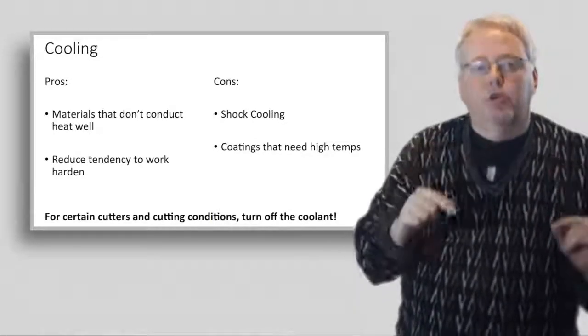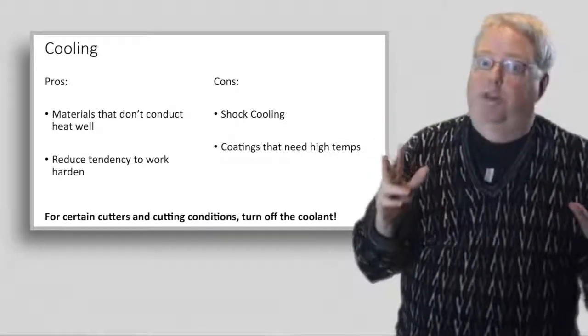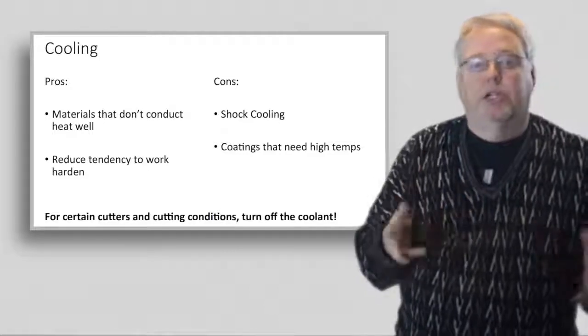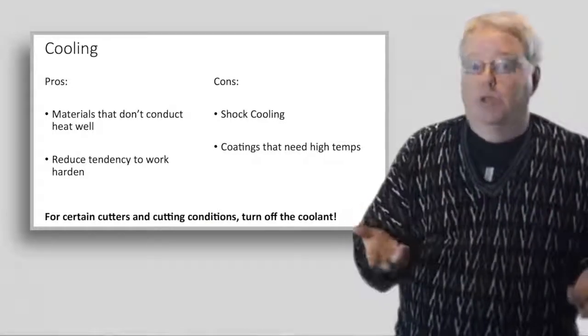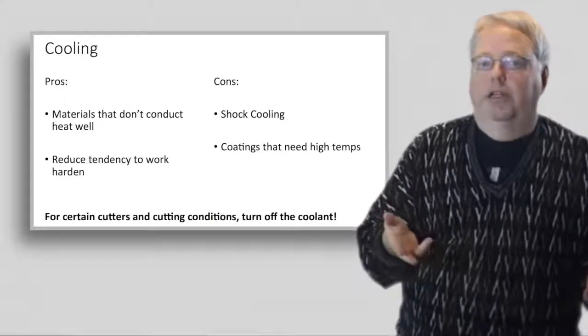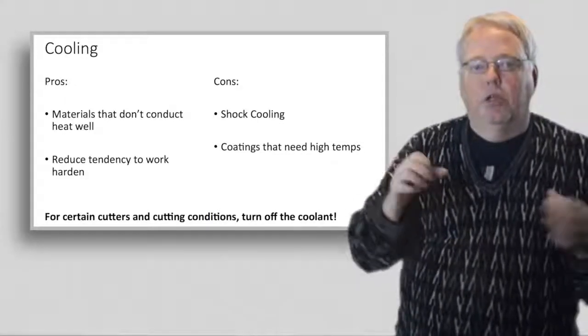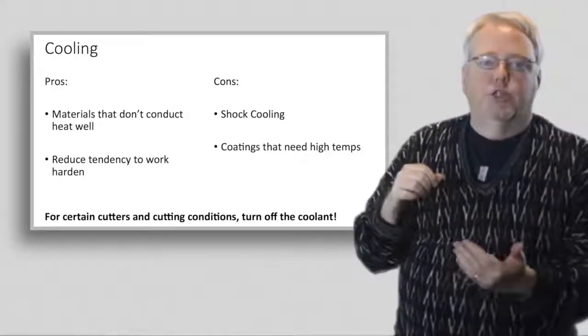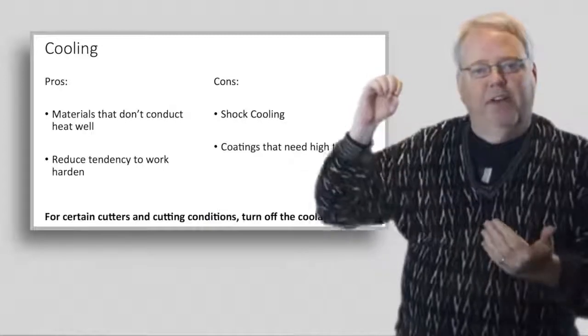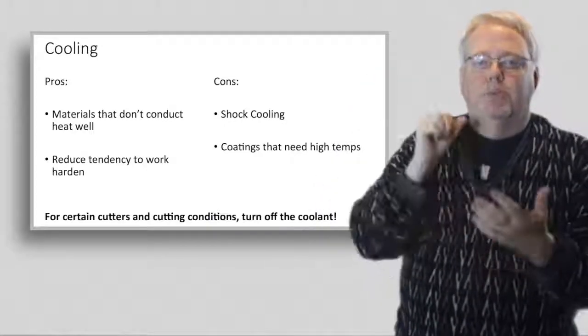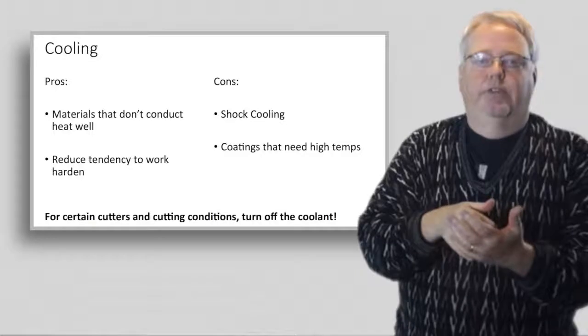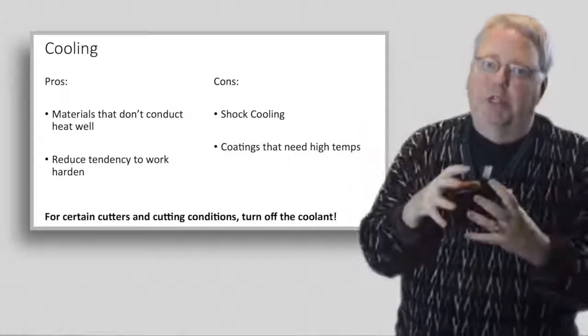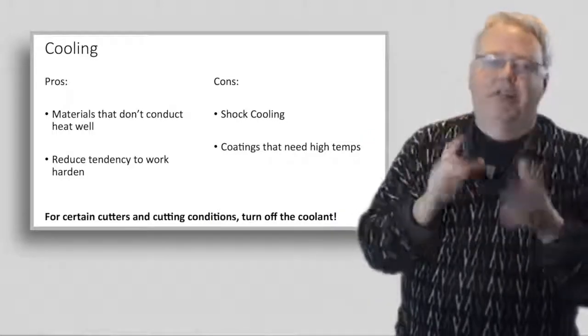But there are downsides. You may have heard that coolant can reduce the life of carbide, particularly with inserts. This is due to something called shock cooling. At microscopic scales, coolant spatters your insert as a series of droplets. So your cutter gets super hot cutting off a chip, and a big fat coolant droplet lands on it, turns to steam, and radically cools the spot where it hits. That's shock cooling. It causes rapid expansion and then rapid contraction of the material that leads to micro cracks, and they can radically shorten your tool life.